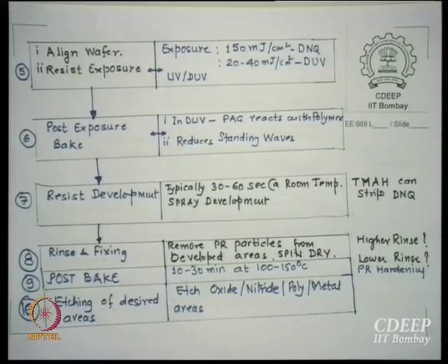If this is not properly baked, when you develop, the resist will go away from everywhere, okay. So this post bake is for 30 minutes at 100 to 120 degrees. Some resists may require 150 degrees, hard bakes, okay. So it depends on the different resists. Then after the resist post bake is given, we put the wafers through